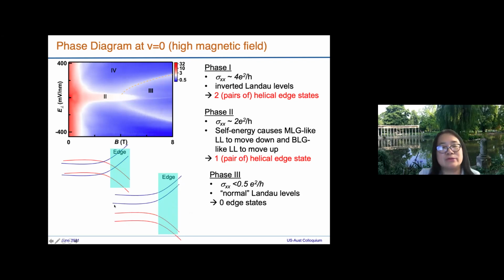And so phase 3, what happens is that basically they continue to move. Now the bands are not inverted anymore. The electron-like band stays above the hole-like band. Now these are just like a normal band structure, and so this becomes an insulator. So this one has no edge states.